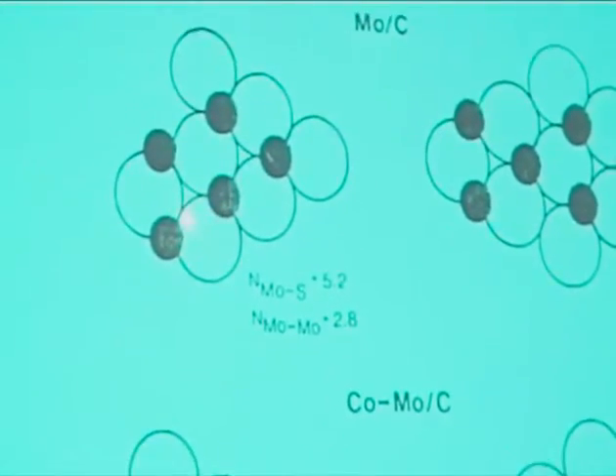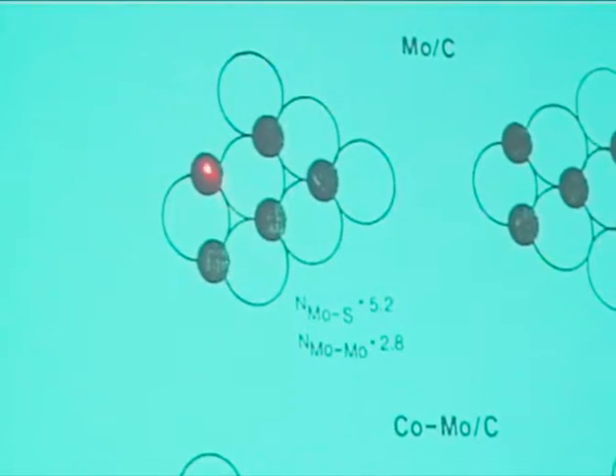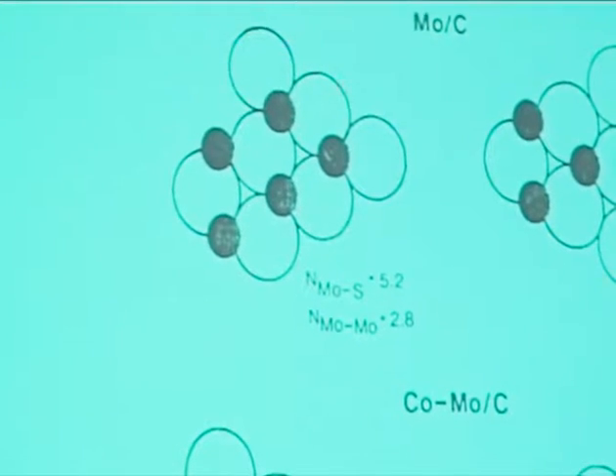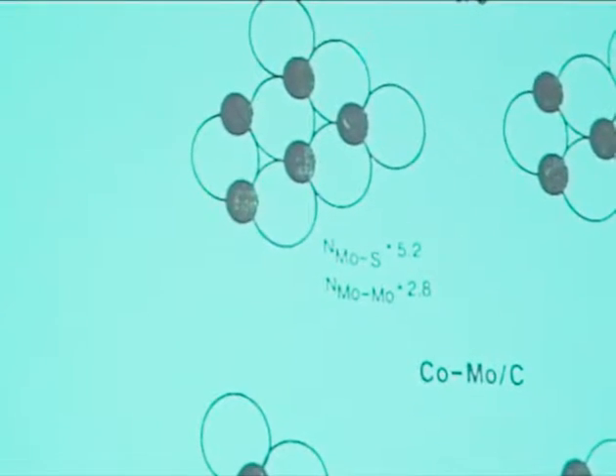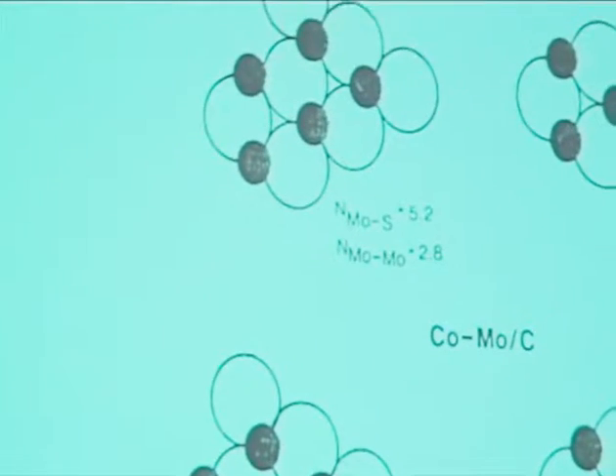We all know from surface science that atoms at the edge of a system are in a different position than in the middle, and they relax. Because at the outside they have vacuum, at the inside they have a force, and that's different from an atom which has forces from all sides. So normally they relax inward, you get contraction. So here we would have expected that, for instance, take this one here, the molybdenum atoms are all at the outside, there is none at the inside. So you would have expected a molybdenum distance which is shorter than the 3.16 of the huge single crystal. And that was not the case. It was perfectly 3.16. So that was already a warning sign.